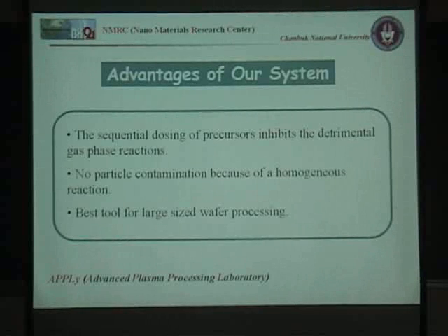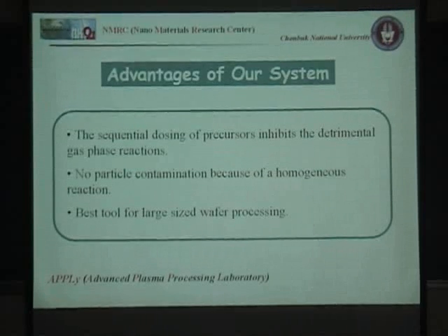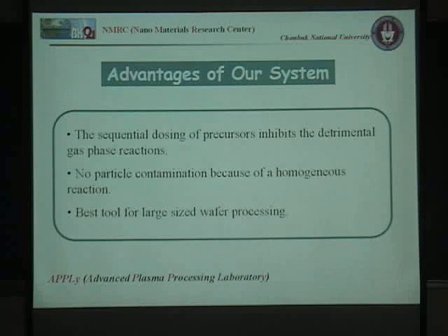this sequential dosing mechanism inhibits the detrimental gas phase reaction, because at every step some byproducts are formed on the substrate, which are purged before dosing the other reactants. Due to these mechanisms, the substrate has very little or no particle contamination because of the homogeneous reaction on the substrate. And our system is best for large size wafer processing.